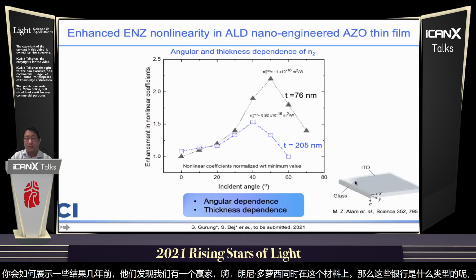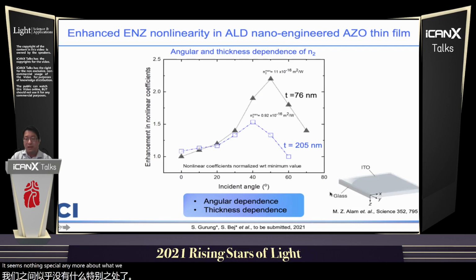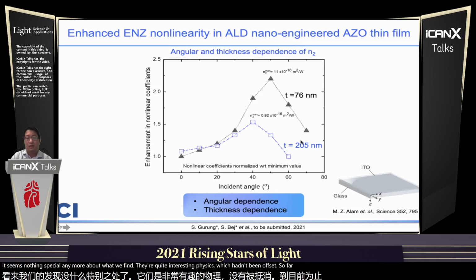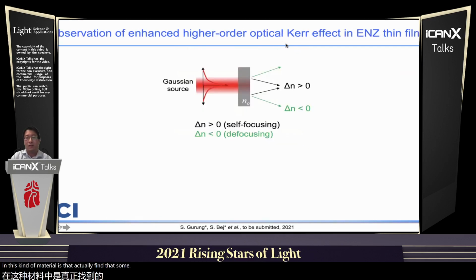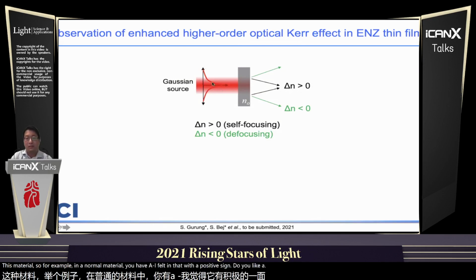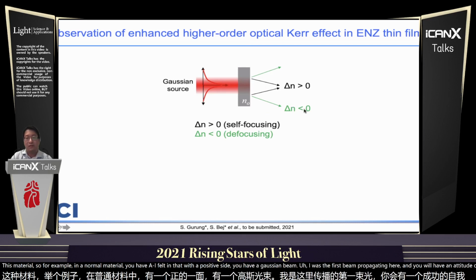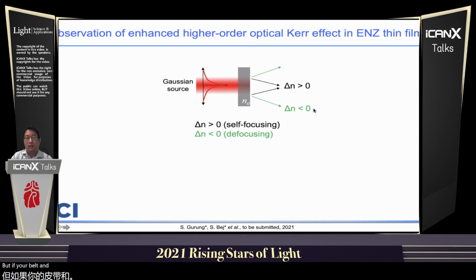It seems nothing special anymore, but what we find is quite interesting physics which hasn't been observed so far in this kind of material: you find there's something like optical Kerr nonlinear, higher order nonlinear effect here in this material. So for example, in a normal material, if you have a delta n with a positive sign, and you have a Gaussian beam, an ultrafast beam propagating here, you will have a self-focusing effect. But if your delta n change is negative, then you have a defocusing effect here.